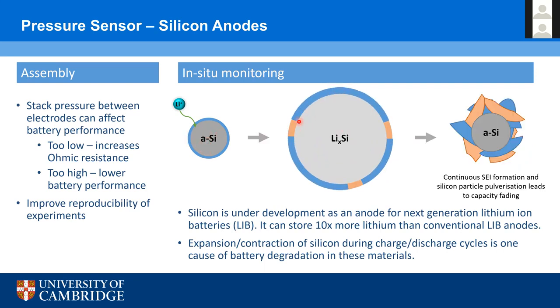This SEI layer, the solid electrolyte interphase layer, is quite fragile, and it fractures and breaks when you re-expand the silicon. When you expose fresh silicon surfaces, you get more SEI forming on the surface. Over multiple cycles, you get this expansion and contraction of the silicon and continuous SEI formation. This is eventually what leads to the death of the battery and increases in impedance and everything.